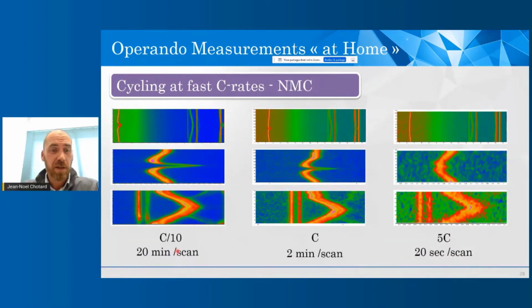But we want to go fast, so 20 minutes per scan is pretty long. So we went down to 2 minutes per scan with a C rate of 1C, so 1 charge in 1 hour. And then we even went faster with a 5C C rate, which means a charge in 12 minutes. And for that, we did 20-second per scan measurements. So of course, intensities are much lower, but still we are able to see very clearly the evolution of the cell parameters during these very fast scans within 20 seconds, which was really not possible before with regular reflection diffractometers. Otherwise, you need to go to the synchrotron.